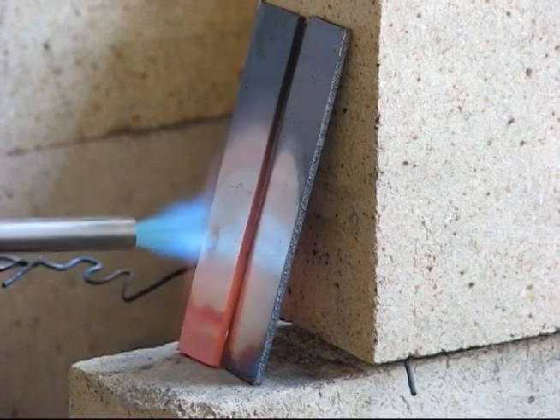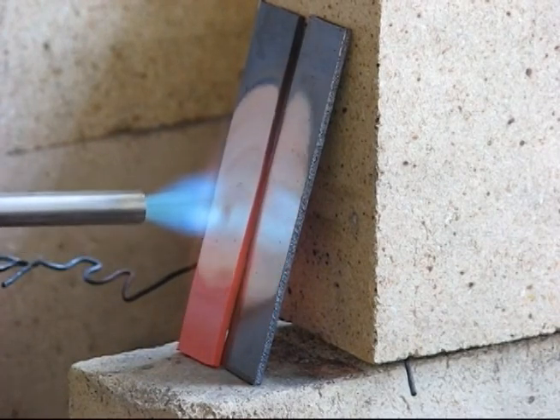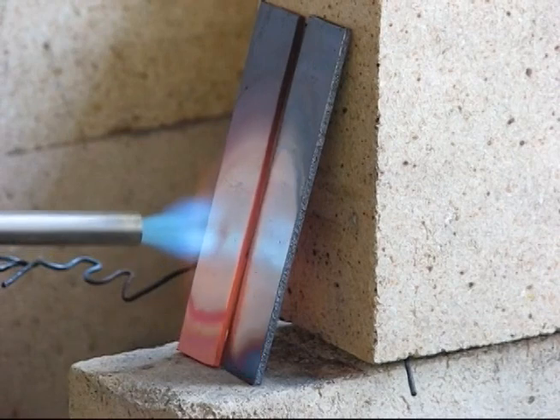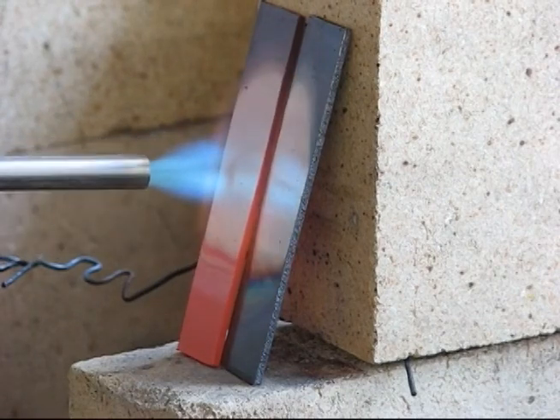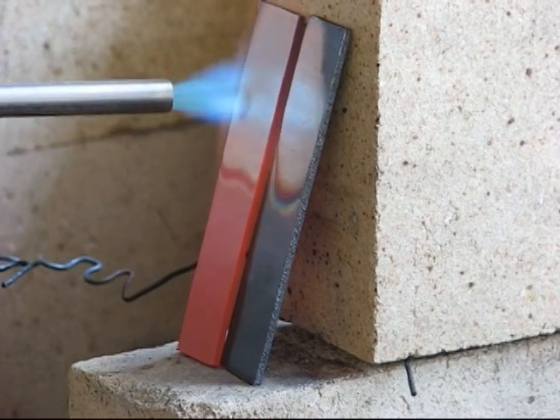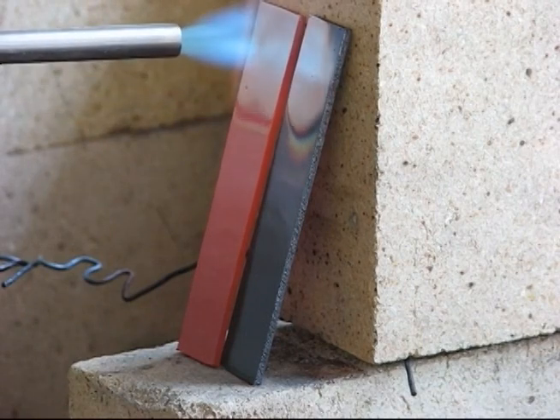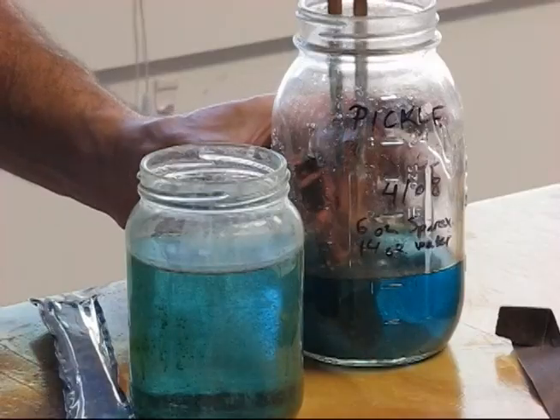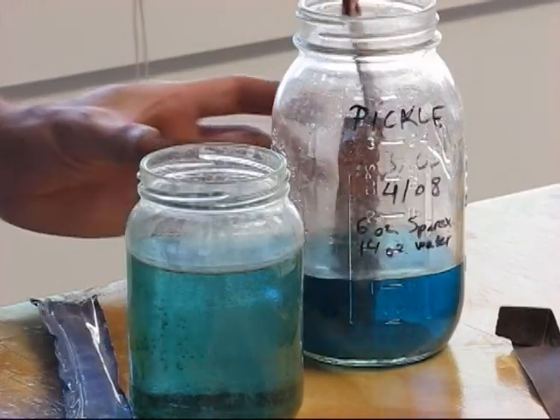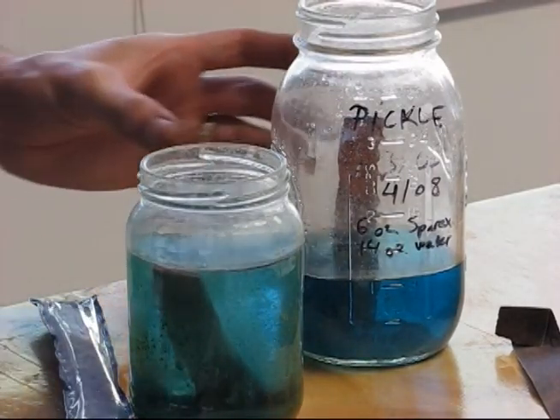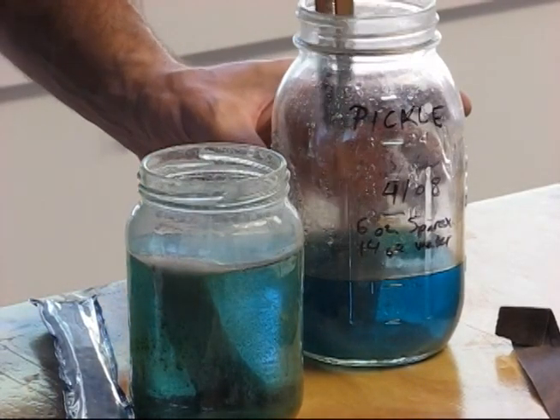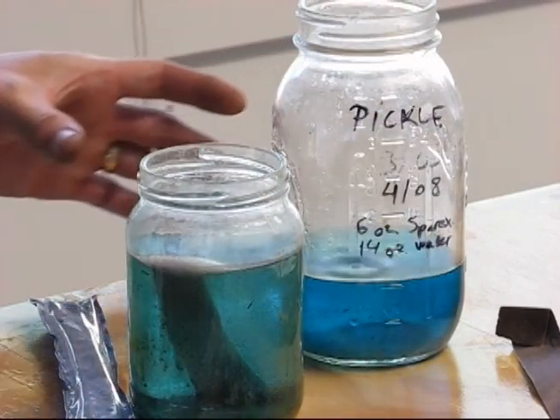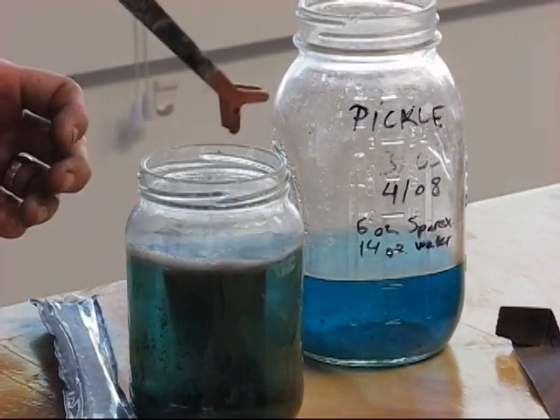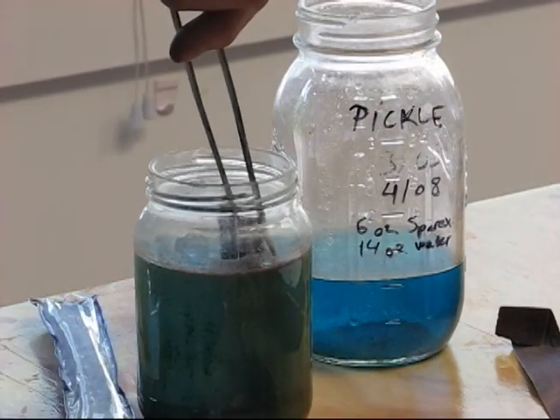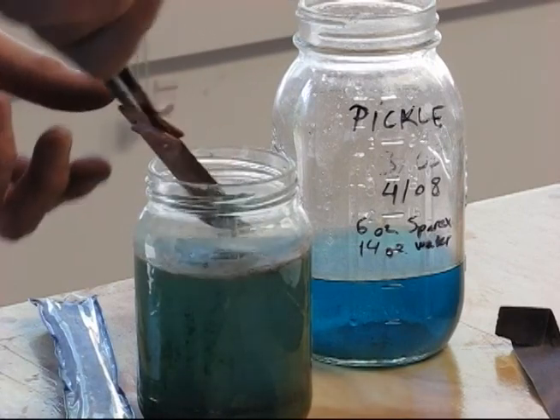Here Jesus is annealing the copper to make it more malleable. Then he pickles the copper to clean the surface oxidation. After a few seconds in a bath of baking soda to neutralize the acid, they are ready for the next step.